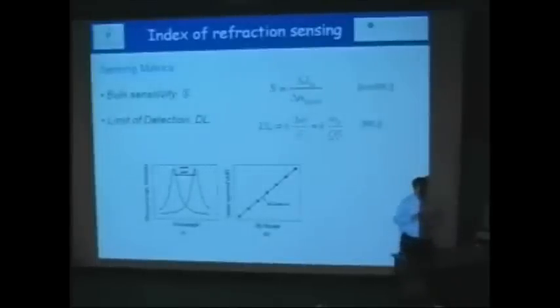The other one is exactly the opposite. The detection limit is an index of refraction unit. So it is a ratio that says if I could measure 10 to the minus 5 change in the index, the lower it is, the better it is. And it is proportional to the delta omega, which is the full-width half max of the peak divided by the sensitivity. So the narrower the peak or the bigger the shift, the better I could get the detection.